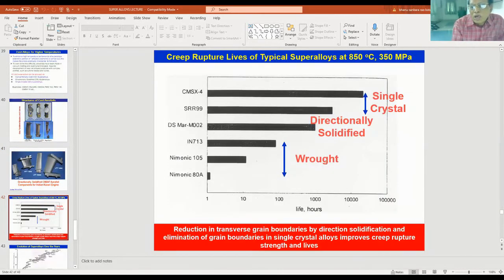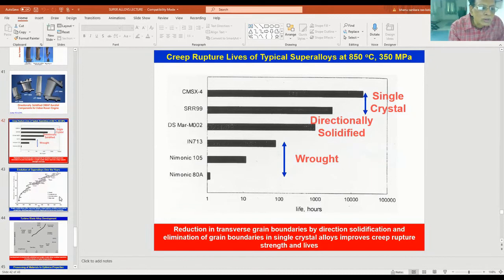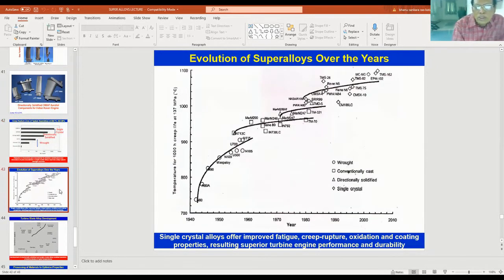See the performance of the wrought alloys, directionally solidified alloys and single crystal alloys. Here you have the name of the superalloy and the creep rupture life at 850 degrees centigrade and 350 megapascals. You see that single crystal superalloys, where we do not have any transverse grain boundaries or no grain boundaries at all, give better creep rupture life compared with wrought alloys, which have the fine grain structure distributed more. You can see here single crystal alloys offer improved fatigue, creep rupture, oxidation, and coating properties, resulting in superior turbine engine performance and durability.